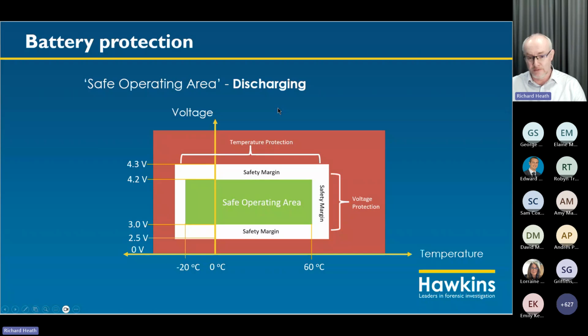And a really important thing with lithium-ion batteries is operating them in the safe operating area. So this chart is really trying to show that there's a range of temperatures and a range of voltages that the cell is quite happy to operate at, and that is the green area in the middle of the chart. If you start to operate it at a voltage or a temperature outside those, either too high or too low, then the cell can be damaged in some way, which either means it goes into thermal runaway, or it might be damaged internally if it's over discharged and the voltage gets too low, and it might go into thermal runaway later on.